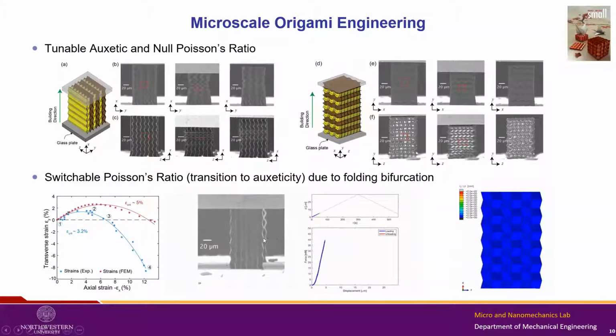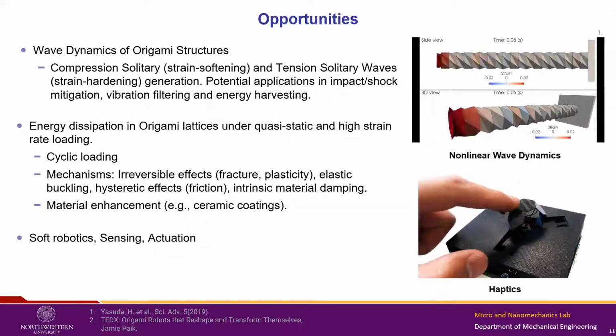So you compress, you can see some expansion in the mid zone, and then that folding bifurcation is triggered, and the structure starts contracting laterally as you compress. So that's what we found, and that's this switchable Poisson's ratio. We also did some continuum modeling, FEM, on these structures, and we were able to recover that. So that's a brief part of the origami work.